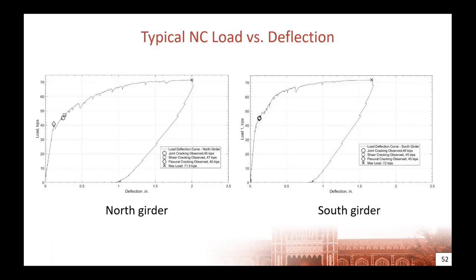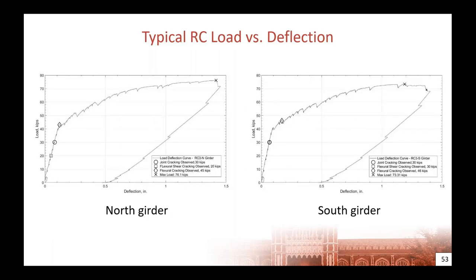In terms of behavior of these specimens, if we look at load deflection for the girders, this is typical for the new construction where we would see an initial linear portion, cracking leading to nonlinear behavior, and then yielding type behavior of our beams. So basically we saw a good flexural failure in our beam specimens for the new construction specimens. We saw the same thing for the retrofit construction specimens.